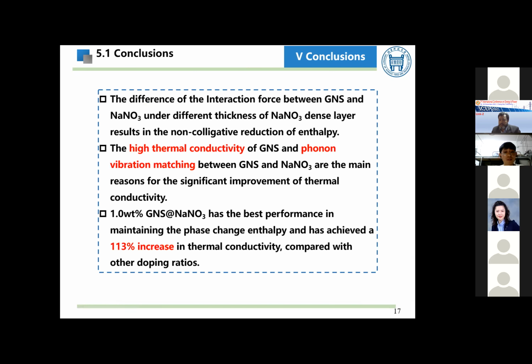The above is all the content of this paper. In general, our conclusions are as follows. The difference of the interaction force between GNS and sodium nitrate under different thickness of the sodium nitrate dense layer results in the non-colligative reduction of enthalpy. The high thermal conductivity of GNS and the phonon vibration matching between GNS and sodium nitrate are the main reasons for the significant improvement of thermal conductivity.